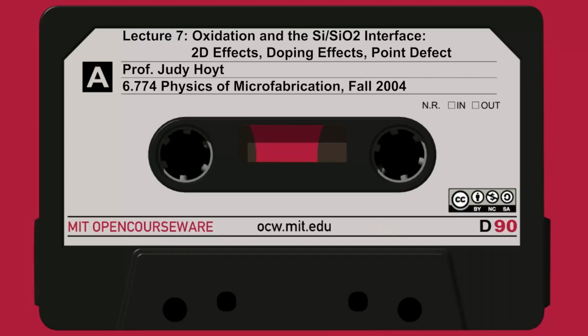Of course, the oxidation rate is going up as well. So this gave people maybe a hint that the faster you oxidize, the more interstitials you're injecting. The oxidation-induced stacking fault growth rate is smaller for lower partial pressures of oxygen. So again, slower oxidation rate. So this is an idea that the rate of oxidation determines the rate of injection of interstitials into the bulk.